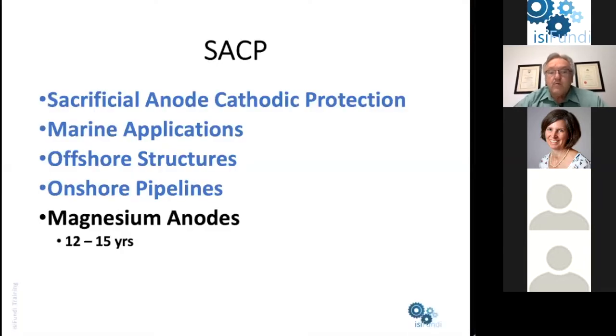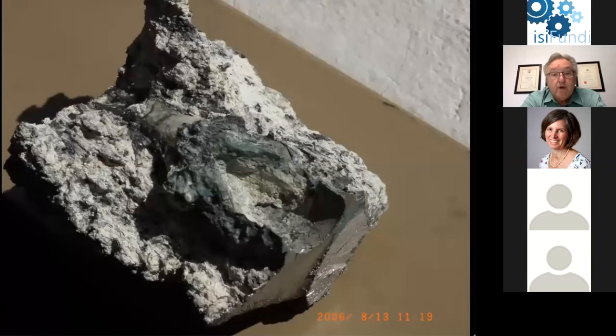One of the issues with magnesium anodes is that they have a relatively short life. And you may say, well, 12 to 15 years, that's long. But not really when you're talking about a pipeline that has an operating life of 40 years minimum. So one of the challenges with magnesium anodes is that they have to be replaced regularly. So what's the alternative? Just before I go on to that, this is why they need to be replaced.